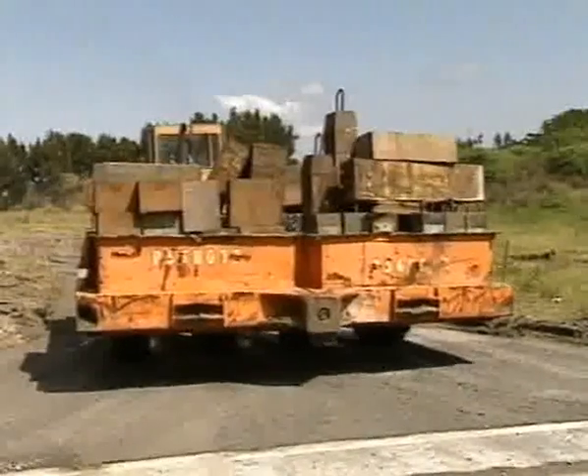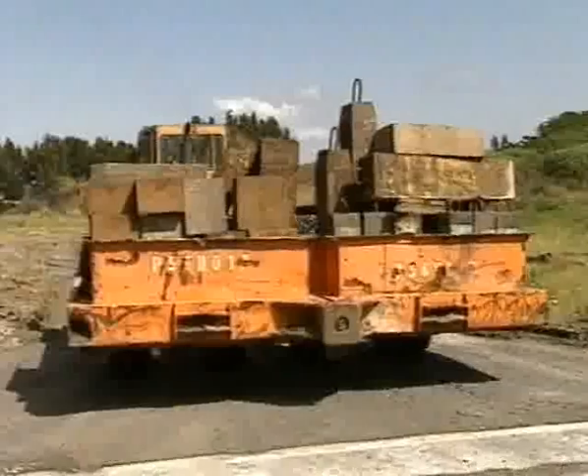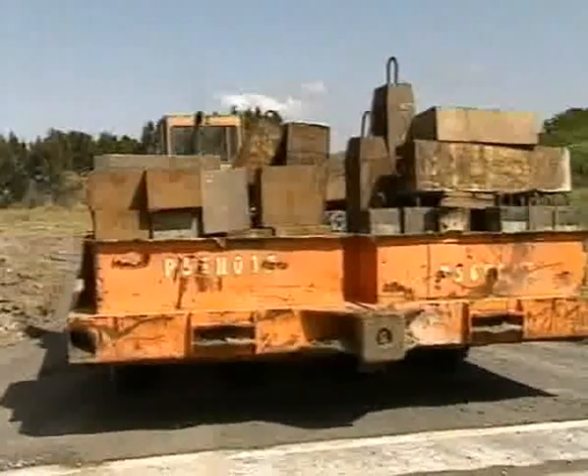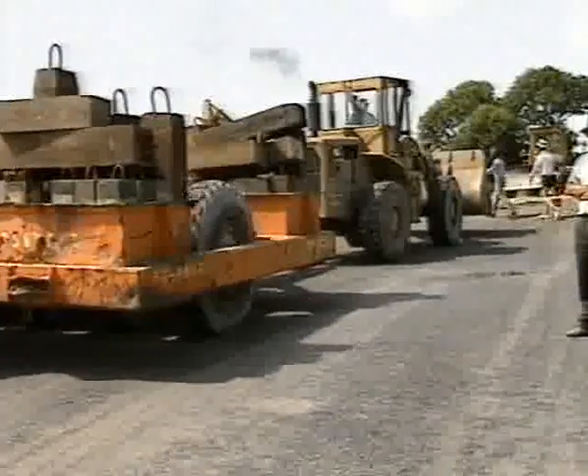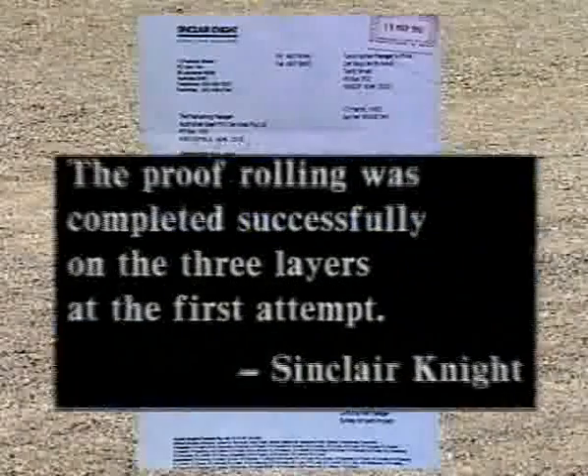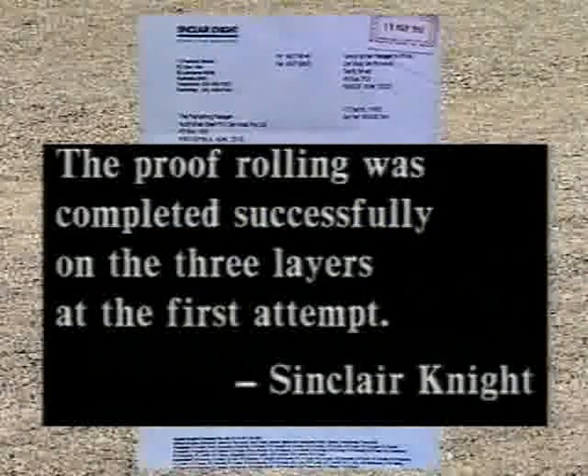The purpose of proof rolling was to assure the material's integrity against breakdown and that the material was not plastic under heavy tyre pressure. Testing after rolling proved the material did not gain in plasticity and minimal particle breakdown occurred. The modest material breakdown which did occur increased the 75 micron size particles, but the gradings were still well within the FAC specified requirements. Proof rolling was completed successfully on all slag placed on the first attempt.